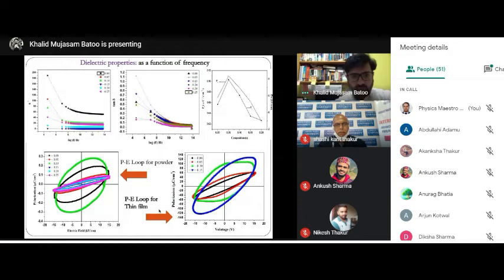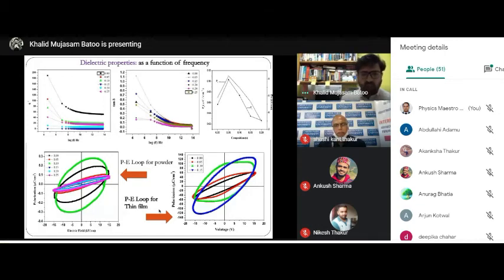So we studied again, not with bismuth this time but with barium, using the same mechanism. We got a very high dielectric constant, a low dielectric loss, and the polarization increased for 5% then decreased as we moved to 20% doping. The polarization versus electric field, however, was again elliptical, not S-type. What we got was very low in the powder material.